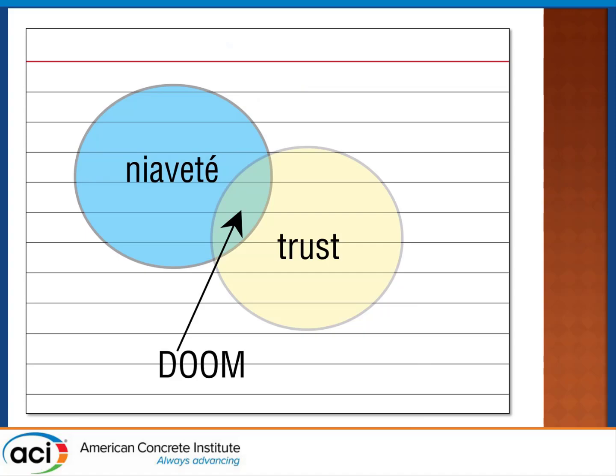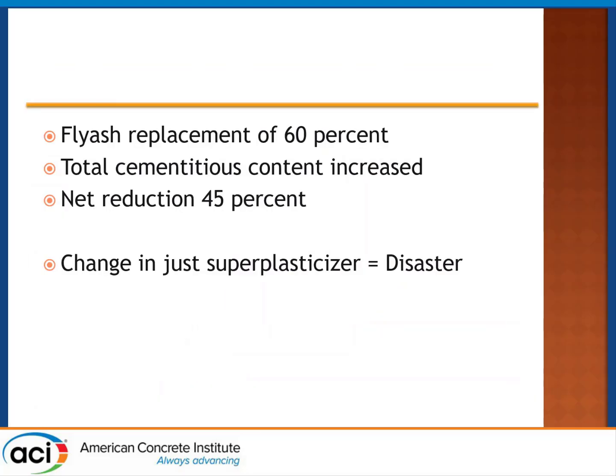The problem is that sometimes you can end up having a problem. Now, this is 20 years ago, and so of course we say, well, we'll go to 60% replacement, but you only want 45, so we'll up the cementitious material, which is not the biggest change. However, I then gave a presentation in a room much like this one, and I put up the mixture proportions, and somebody very carefully transcribed them down in writing. And then they said, now I have a recipe for making that high volume fly ash concrete.